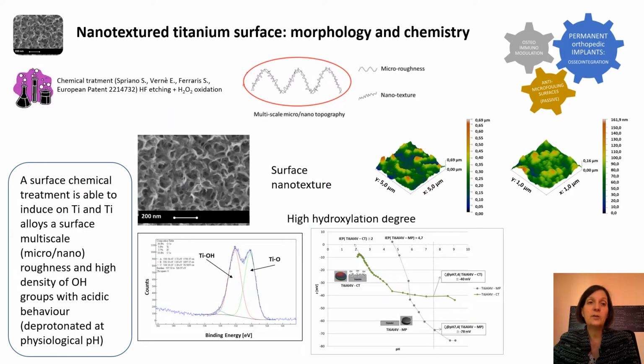At first, we developed a nanotextured titanium surface through a patented chemical treatment consisting of an acid etching and then oxidation in hydrogen peroxide. The first result is a surface with a multi-scale topography. That means a roughness on the microscale and then a second roughness on the nanoscale. You can see it in this SEM picture, and here the AFM topography of the surface. You can see the micro topography that is in any case below 1 micron. That is almost assessed as the best roughness for bone-implant contact, avoiding the risk of fatigue fracture. And you can see also the topography on the nanoscale.